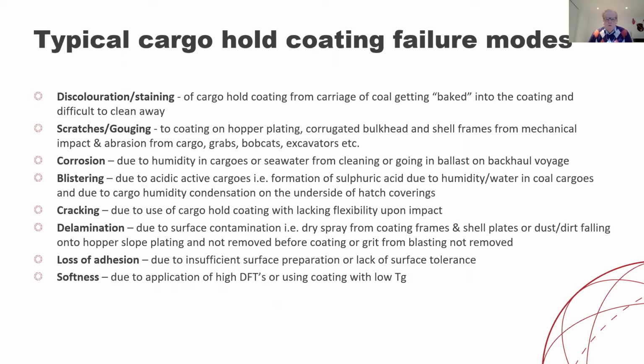Typical cargo hold coating failure modes. Discoloration staining, as already mentioned, is like when you have carried coal and it gets baked into the coating, and it's difficult to clean away. And like Mark already said, if you don't clean and you're taking another cold cargo, it gets even more baked in because of the high temperature that the cargo potentially has when you pick it up.